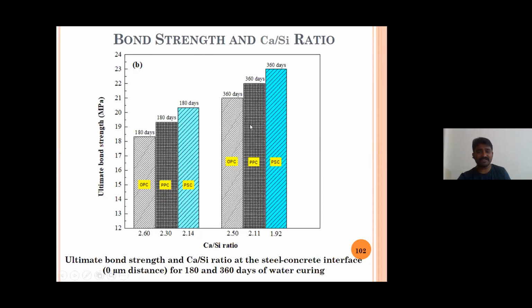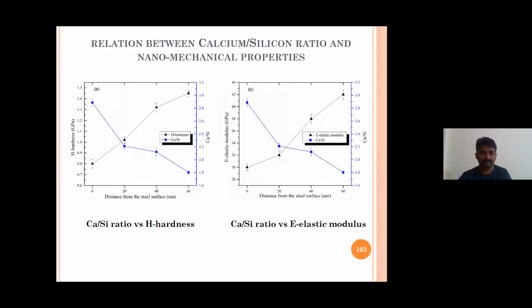So at 360 days, the Ca by Si ratio is still reducing. In the same way, the bond strength is increasing. This concludes that as the Ca by Si ratio reduces, that infers that the calcium hydroxide content is reducing. Because of that, the bond strength is increasing. In the same way, we have done some studies with nanomechanical properties also. As the Ca by Si ratio is decreasing, the hardness is increasing. The same goes for elastic modulus also.